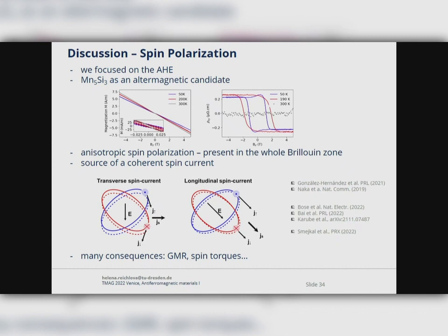So the last thing I want to comment on is that I showed this anomalous Hall effect in our Mn5Si3, but even more important are probably the spin currents, which we need and which are in the end the basis for spin transfer torque and GMR. And these are indeed predicted in altermagnets. Moreover, they are anisotropic, so they depend on which direction we apply the electric field. We can generate a transversal spin current or a longitudinal spin current. Here one can see that these ellipses are off-centered differently, so the excess of the spin generates a total spin current. And the first experimental evidence was already presented by these three groups.